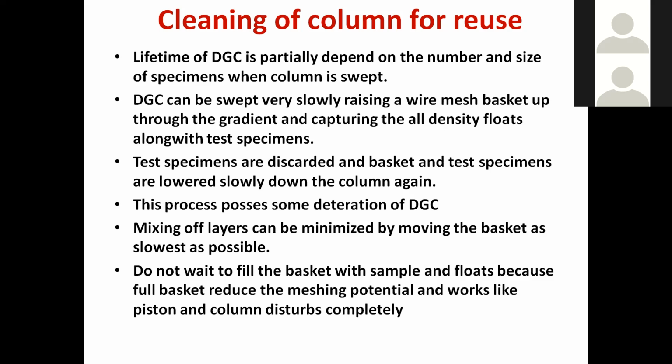This is another point. When will you lift the basket? Is it full? No. If the basket is completely loaded, when you lift the basket, it will work just like a piston, and through the holes of the mesh at the bottom of that basket, liquid will not pass easily. So what will happen? All layers of that column will be disturbed.